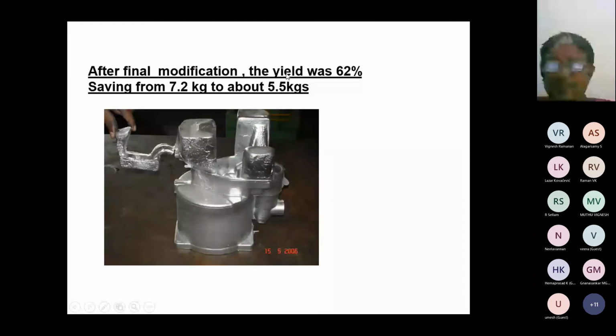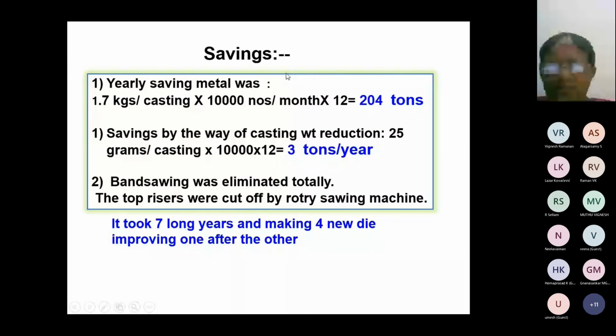Let us work out the savings. The metal saving was 1.7 kg per casting, and 10,000 numbers per month. In 12 months, 204 tons of metal you don't have to buy at all. At the time, the metal price was about 110 rupees per kilo, or even 100 rupees per kilo. By saving 25 grams by putting a core hole, about 3 tons of material has been removed per year. Band sawing was totally eliminated and the top risers have been cut by rotary sawing.